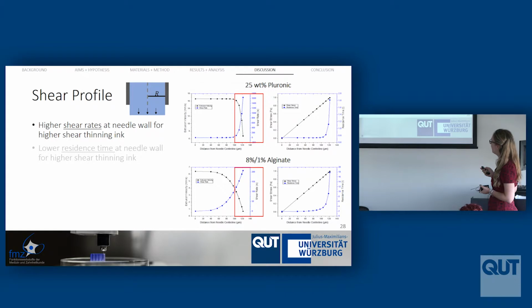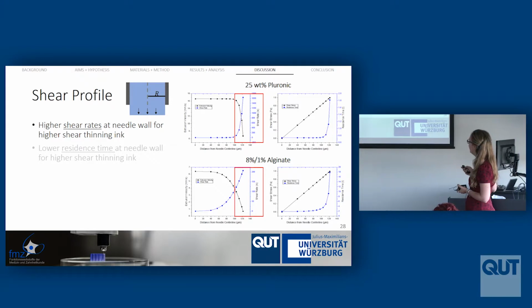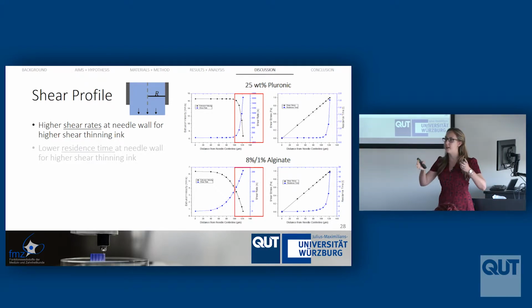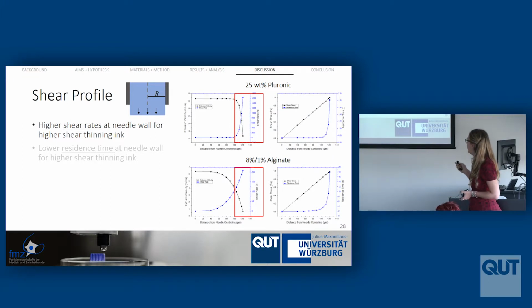This is a really interesting observation. So this is looking at the center of the needle here, in the middle, and then looking across the radius. The wall of it is out here at 140 microns. At the needle wall, we see this blue line of the shear rate increases towards the edge, which means there are very high forces at the edge of the needle and low forces in the middle. And this is what potentially could be killing our cells as we're trying to print them. So we need to mitigate this.